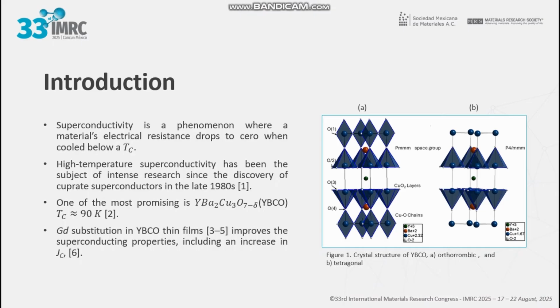And as you can see in the figure, if the structure is properly oxygenated, then its crystal structure is orthorhombic and it has a higher Tc than if it were not properly oxygenated and its structure were tetragonal. In this current work, what we do is substitute the yttrium atoms with gadolinium, and this has been shown to improve superconducting properties in thin films as well as the critical current they can hold.